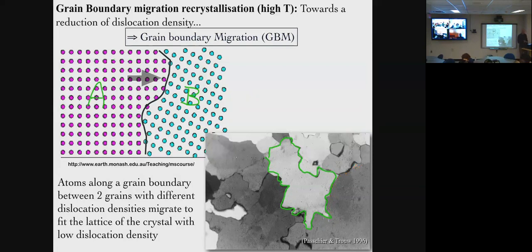So, Renaud? Yeah, one thing I would add is that bulging is usually really, really small scale compared to grain boundary migration. With bulging, you'll have extremely small bulges compared to the original grain, like 2, 3 orders of magnitude smaller, whereas grain boundary migration will involve a fairly large grain. Keep in mind also that as we go from regime 1 to regime 2 to regime 3, grain size increases because we're at higher temperature and the dynamic recrystallization will produce much larger crystals through deformation and metamorphism, okay? And grain boundary migration really involves all the grain boundaries.